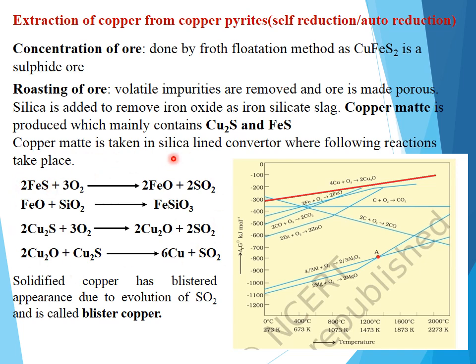Why we take a silica lined converter is that whatever ferrous sulfide is left out is again oxidized to ferrous oxide first. Later on, the ferrous oxide combines with the silica lining of the converter to form slag. This is the way we remove the complete oxides of iron from this mixture. So the first reaction shows how ferrous sulfide is oxidized to produce ferrous oxide, giving out sulfur dioxide gas, and that ferrous oxide combines with the silica lining and produces ferrous silicate slag.